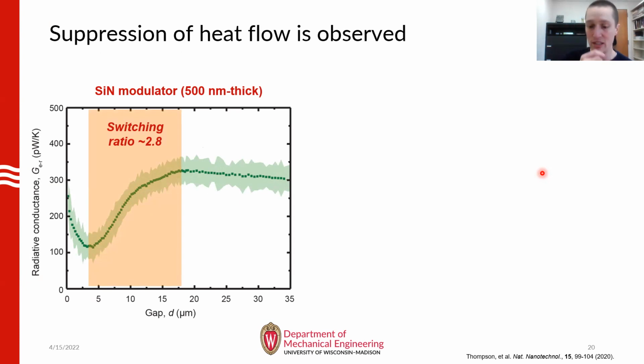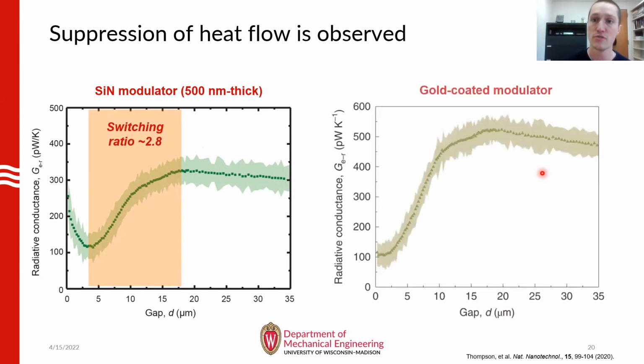Now, this result isn't only limited to silicon nitride. We repeated this experiment with a modulator that was coated with gold. And you can see the results for the gold-coated modulator on the right here. So in this case, we can actually achieve even better switching ratio with a factor of around 5.